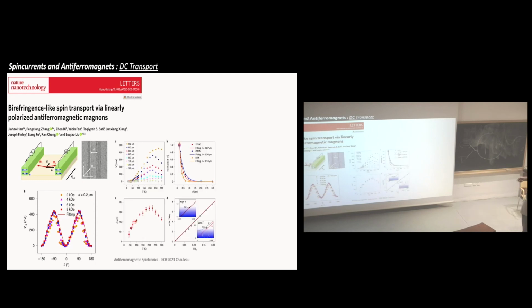What they have done is measure the current they detect as a function of the temperature and for different spacing of the electrodes. By doing this, they could put these figures, and what they have here is the decay length, the characteristic length of propagation of the spin information. They plot it as a function of the temperature, and you see that you have an increase and then after a decrease. And the nice thing here is they explain it in the following way.